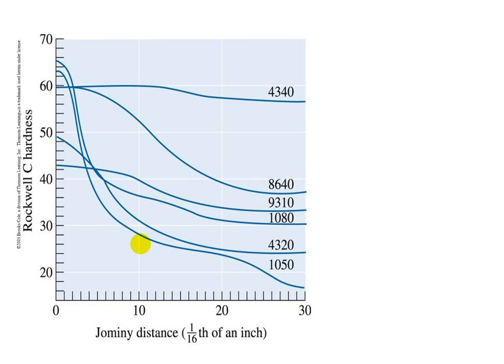We will not get martensite. Therefore the nose of the TTT diagram has not been shifted to the right side. If you think about 1050, you can see only at the very very fast cooling rate, meaning it goes from austenitizing temperature to room temperature maybe in a second, you can possibly get martensite. So such a material we define it as not very hardenable, versus if you have 4340, you can see that at almost every cooling rate, which is any Jominy distance, you relatively get a very high hardness.